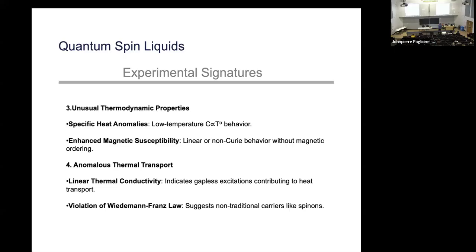So that technique is also very important as a complementary technique to understand whether an actual candidate is a true quantum spin liquid, is proximate to a quantum spin liquid, or is basically not a quantum spin liquid, just a system that, for example, freezes into a particular pattern and is a spin glass. Because if the system freezes into a particular pattern, it is not dynamic, but still it is disordered. So you're not going to see magnetic Bragg peaks if you try to measure that compound.